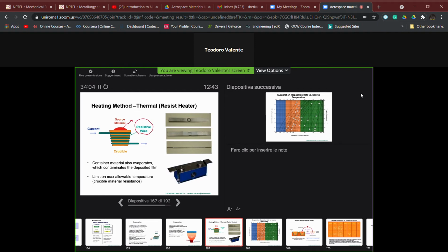source materials. We can also have some contemporary evaporation of the materials with which the crucible has been fabricated. And this can represent a drawback, because we will have contaminants in the deposited film. And so this again goes in the direction of not stressing too much the materials of the crucible, that is, putting low melting point materials inside the crucible itself in order to limit the maximum allowable temperature, and thus also limit the concentration of contaminants coming from the crucible, which can have undesired effects on the coating's final composition.